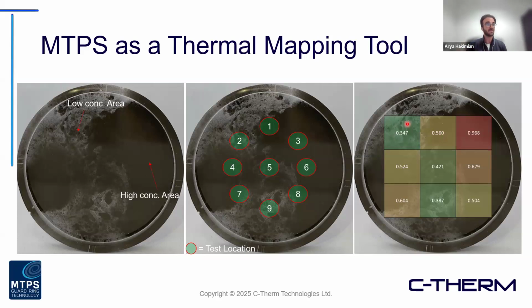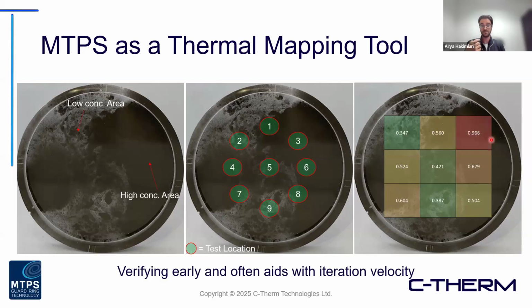dispersion. So we're showing here, the area in the top left, kind of over here, very little filler. It's coming in at one of the lower values compared to the top right here, much more densely populated with that conductive additive, giving us a value almost 3 times higher. So all this is to show, if you have a material that maybe isn't as easily visibly detectable, maybe you're dealing with an opaque base, we can't just look at it and pick up on these issues. The MTPS can be a tool that allows you to very early on assist with that iteration velocity. So as you're formulating, going through different stages of product iteration, you can pick up on some of these issues earlier on so they don't end up coming back to bite you later in that development cycle.